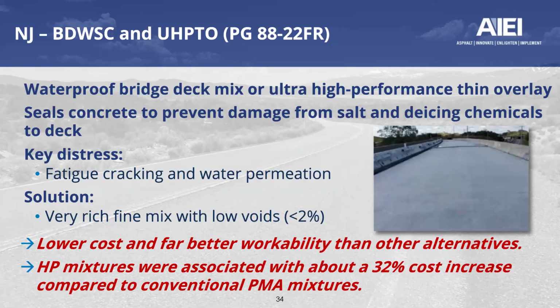And I'll pause there for a moment. You'll notice that there is a bit of a trend in that relationship. Both fine mixes and low air voids is a reoccurring theme in the 5 states that we visited. They do find that this is a cheaper option for them as compared to other alternatives. However, if you compare it to other polymer modified mixes in the state of New Jersey, there's nearly a third of a premium that they're paying at about 32%.